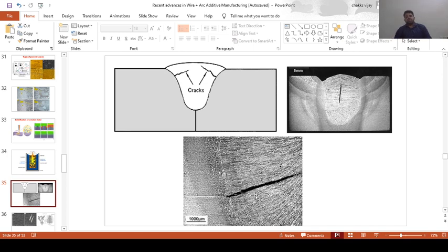Generally, if we are using aluminium, we go for an aluminium silicon wire, especially to weld aluminium. What is the reason? The silicon will reduce the melting point of aluminium and improve the surface wettability. The surface wettability will result in more interdendritic liquid formation. When there is more interdendritic liquid, it will potentially heal all these cracks and voids very effectively. That's why we generally go for aluminium silicon wire, like ER4043 wire.